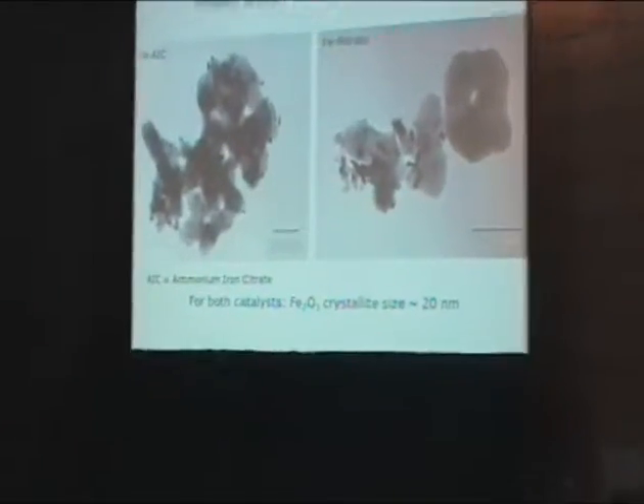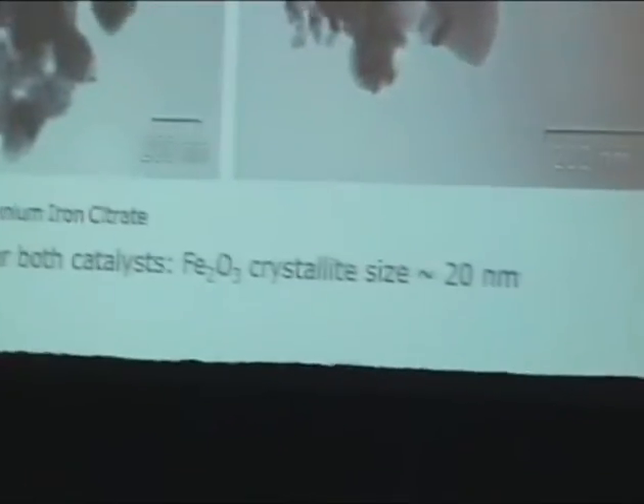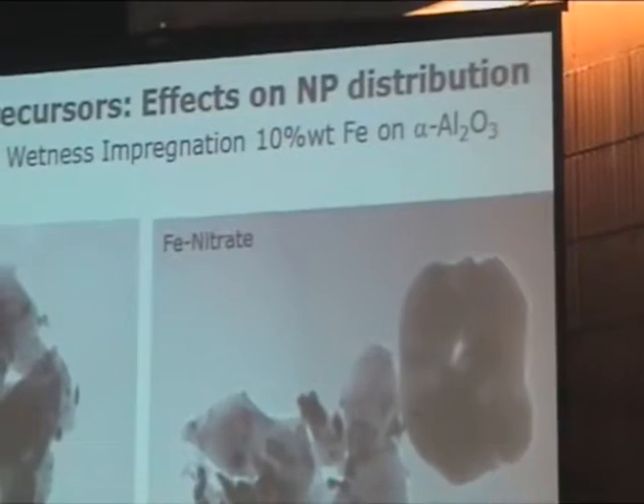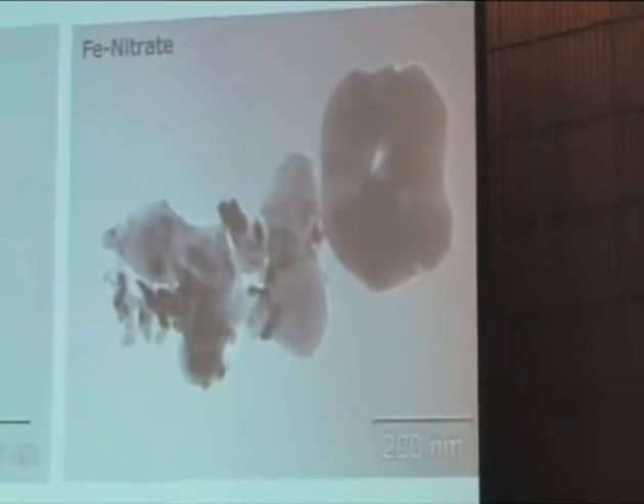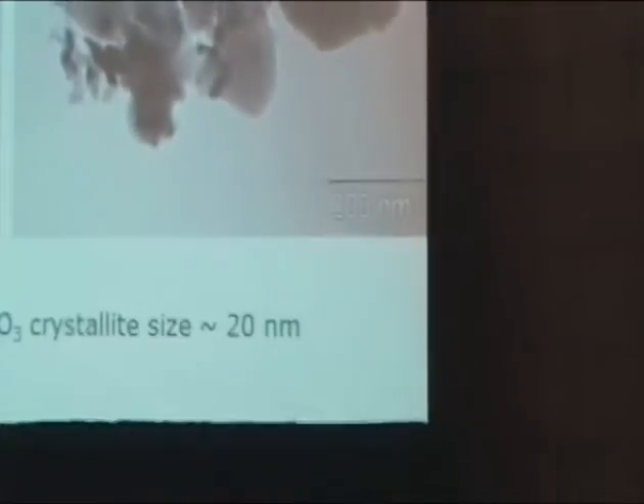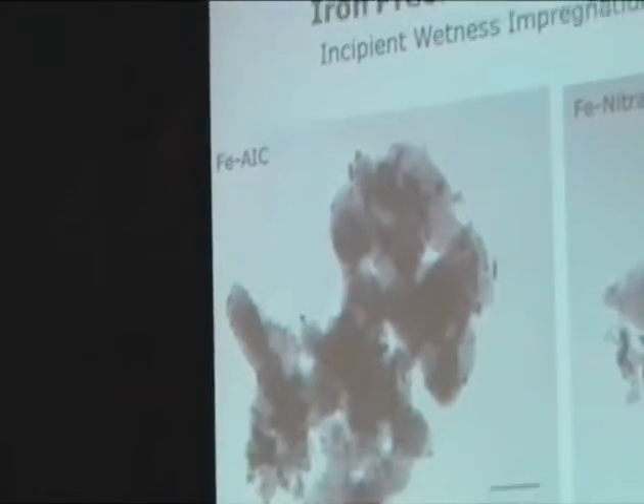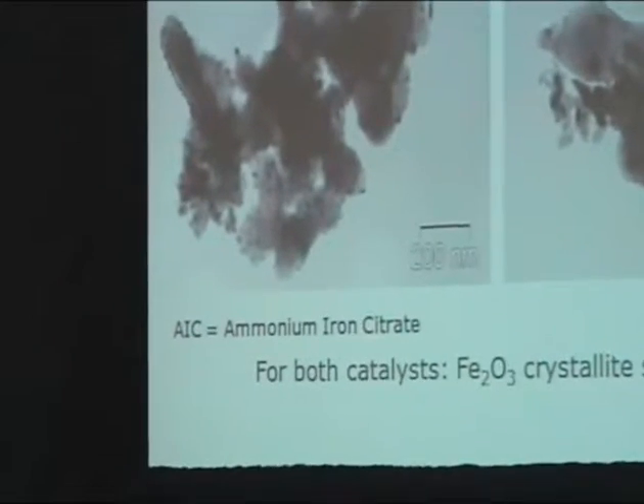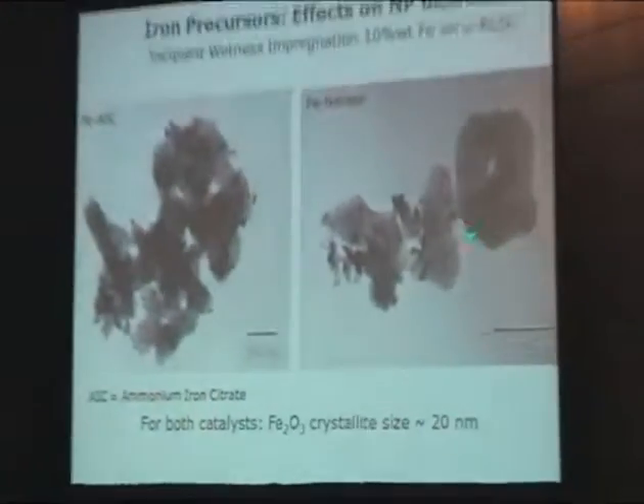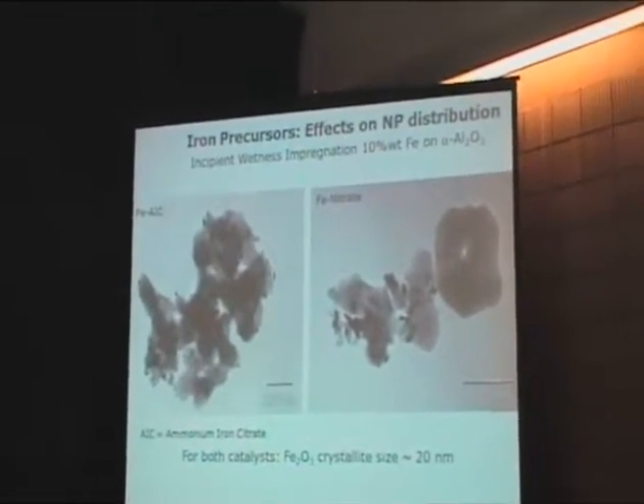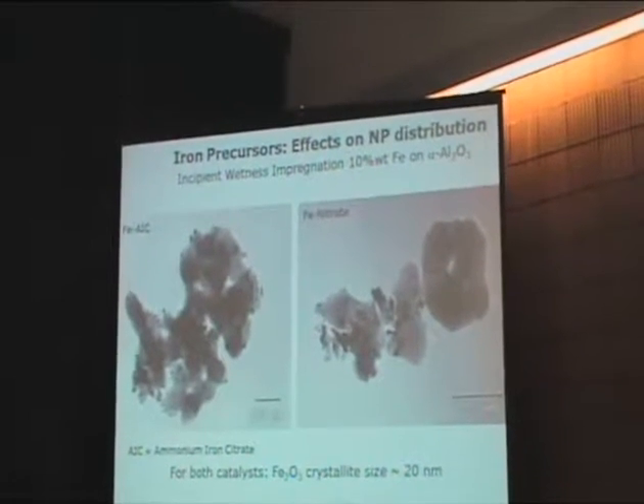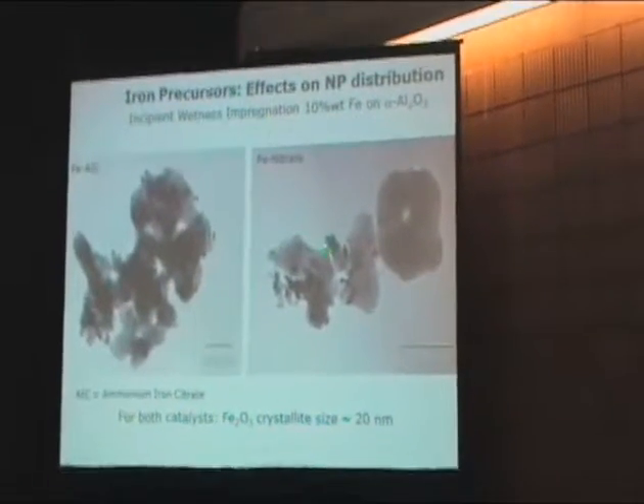Finally, the effects of the nanoparticle distribution. Again, our alpha alumina support with particles of 100 to 200 nanometers, so a typical specific surface area of about 10 square meters per gram. If we impregnate iron nitrate, we observe alpha alumina particles that give a very smooth appearance. That implies there's hardly any iron oxide present on that support particle. On the other hand, this support particle is heavily loaded with iron oxide, as was also confirmed by EDX.